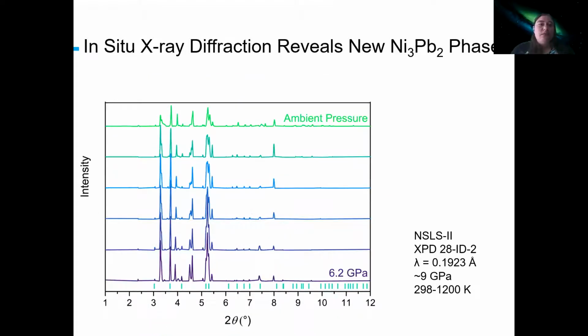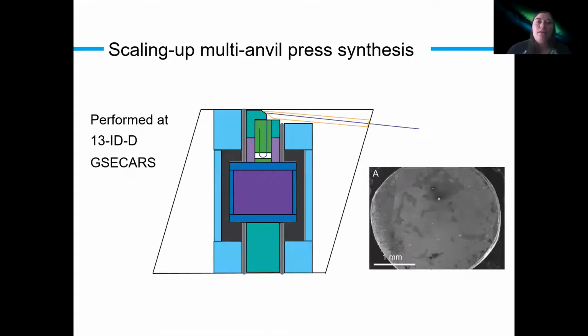We also then decompressed this, and there are fewer of these diffraction patterns because we're dealing with realigning the entire 1,000-ton press in the X-ray beam. But we do see that this phase continues to stick around, and here is the major peak for that phase.